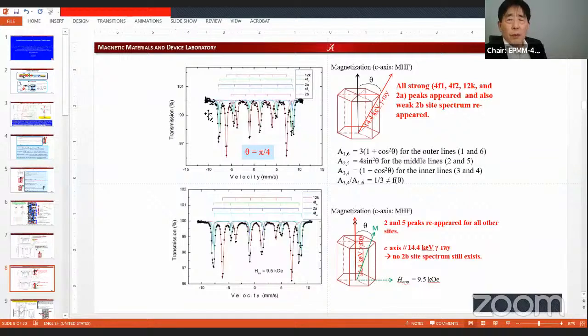This one is also from barium ferrite. Once we apply a different angle of this gamma ray against the c-axis of the hexaferrite, you will see a different hyperfine field here. Look at here, the hyperfine field from B1 and B6 here is much larger than that. That means the magnetization is much larger than that, depending on the applied magnetic field against the c-axis of the hexaferrite.